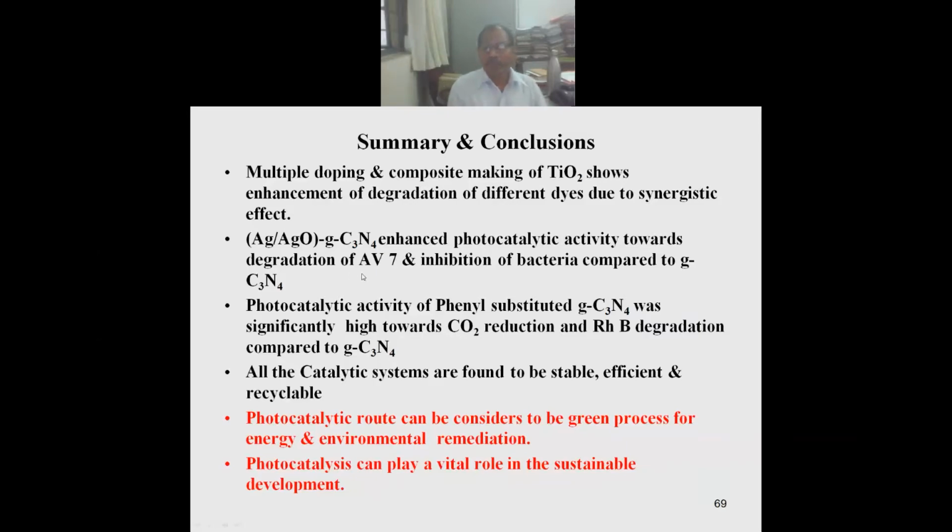So we have seen so far the modification of TiO2 and modification of GC3N4. TiO2 is anatase, which is UV active. We tried multi-doping with metallic and non-metallic dopants, and brought the band gap to a lower value, into the UV-visible region, with better stability.